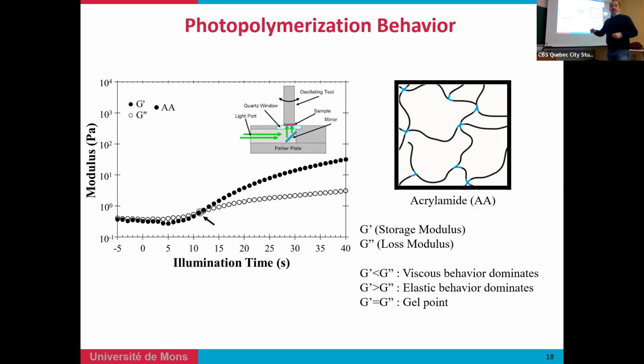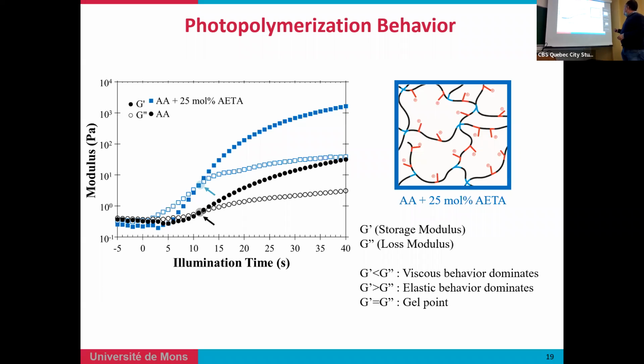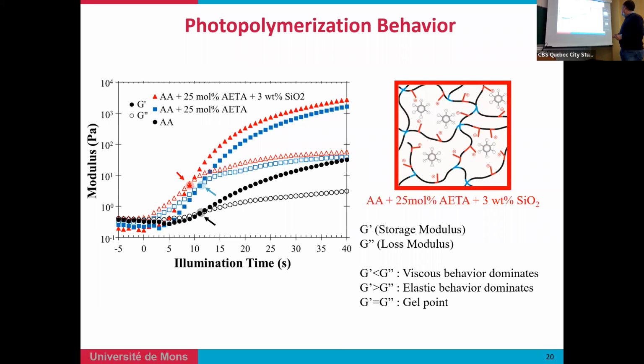We have shown, by playing with the composition - the acrylamide being the main component used for making such gel - when you add AETA, you can see a certain improvement and increase of the modulus. But of course, when you add nanofillers, as expected, you increase the stiffness such that you can see the storage modulus increasing a lot.